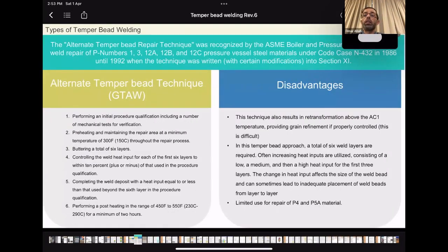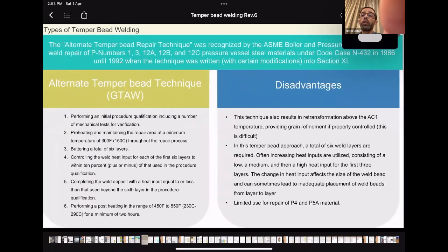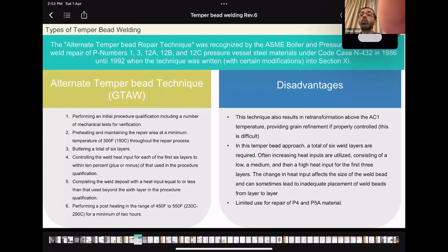And in 1986, a new temper bead technique was developed, which is the alternate temper bead repair technique. So it was called alternate because it was an alternative to the well-known half bead technique. So it was recognized by ASME through a code case for P number 1 and 3, 12A, 12B, and 12C under the code case N-432 in 1986 until 1992. So this technique was used extensively between 1986 and